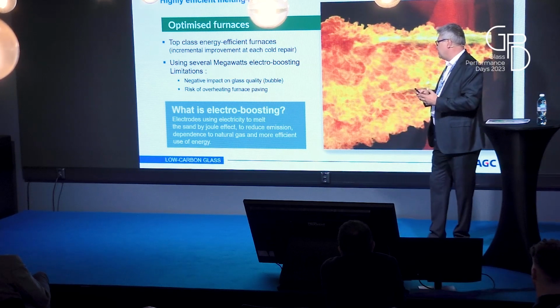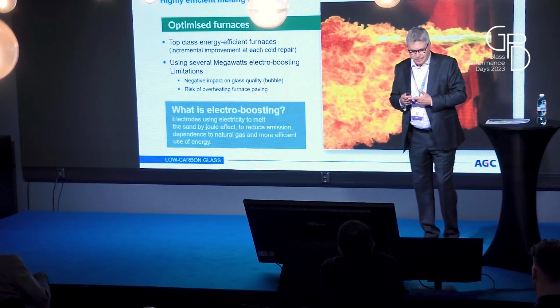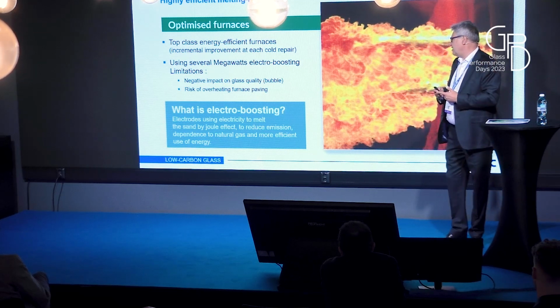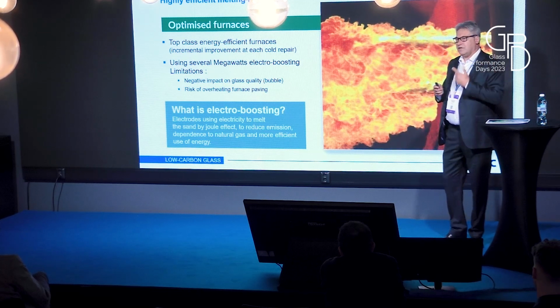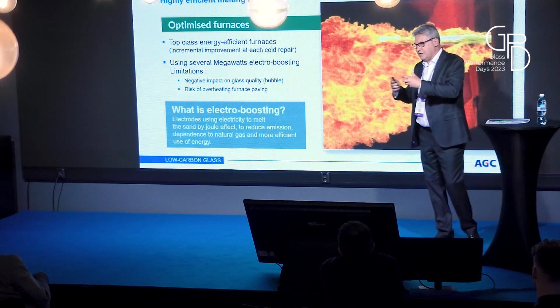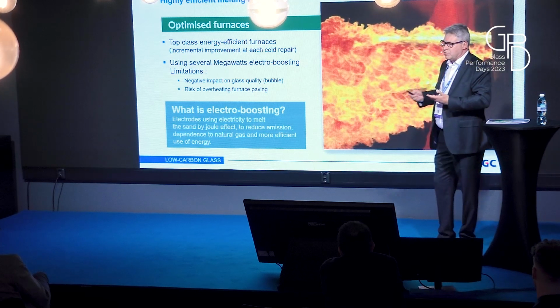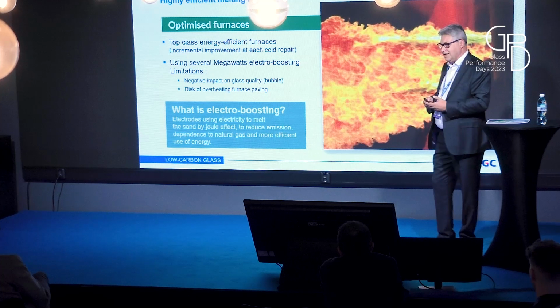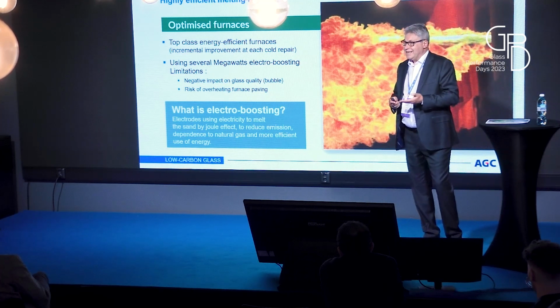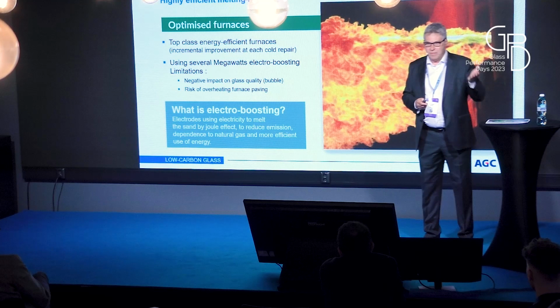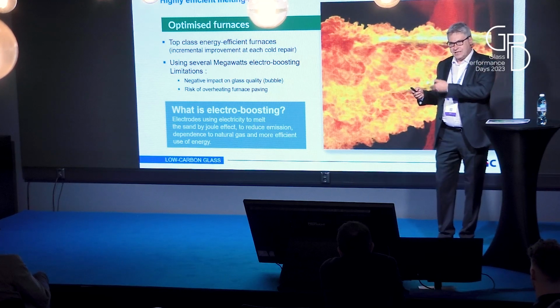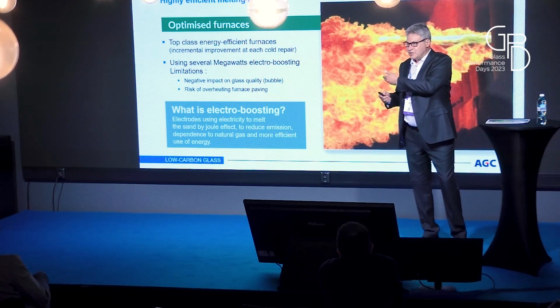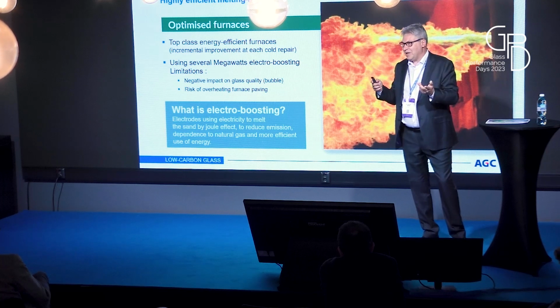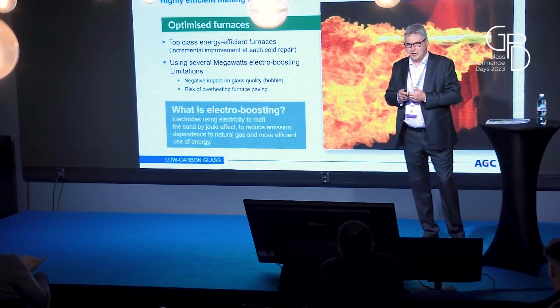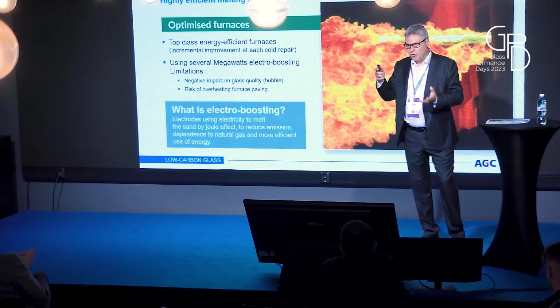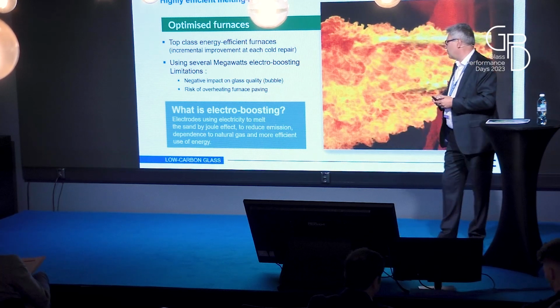There are different negative impacts. One is the quality. For sure, electro-boosting has a negative impact on quality: it generates a lot of bubbles, and there is also some risk of local overheating. When you decrease the quality of glass, it means you melt raw material to finally produce glass with defects that you will reject. So finally, the CO2 balance is influenced, and it's badly influenced. So we always have to consider this quality aspect.